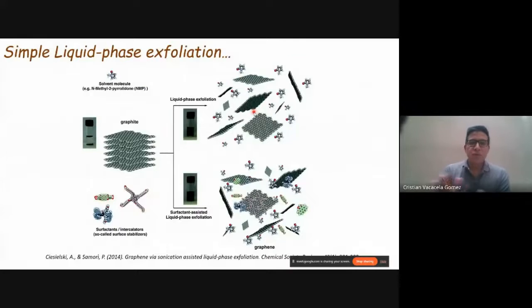And now let's move to the different methods, working with liquid phase exfoliation. What is the idea? Let me repeat again. We have, for example, polar solvents and water. We can introduce graphite into these solvents and apply the sonication process, and these mechanical waves increase the distance between the planes and it starts the exfoliation of graphene.